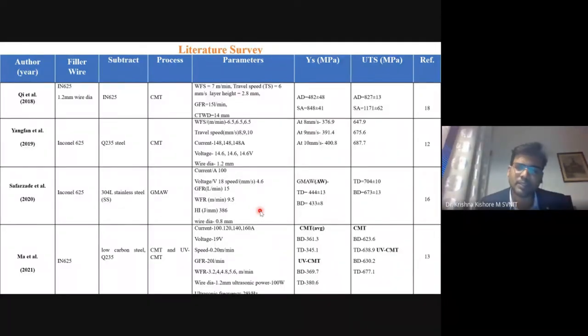This Inconel alloy is quite widely used in defense and naval applications, where a good amount of research has already happened in this area, but there are still some interesting factors which we will be seeing. Still there is a challenge to achieve a uniform microstructure, and also a good challenge to avoid this kind of staircase effect in the case of WAAM of Inconel 625 alloy. People have done Inconel 625 depositions for quite a good number of applications. As per our survey of the existing literature, we have observed that most people prefer cold metal transfer. And one good advantage of cold metal transfer is that the pulsing conditions which we can control are quite high, right?